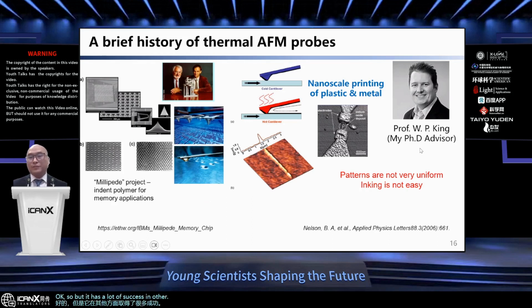So my PhD advisor, Professor William P. King at the University of Illinois, applied these thermal AFM probes for nanoscale printing. This is a paper in 2006 published by Professor King. Using a thermal AFM probe, you can deposit nanoscale patterns of low melting point metal or polymer.